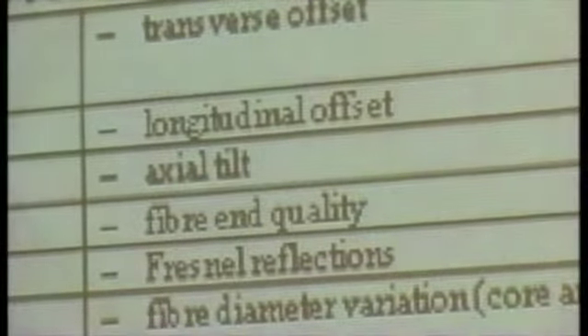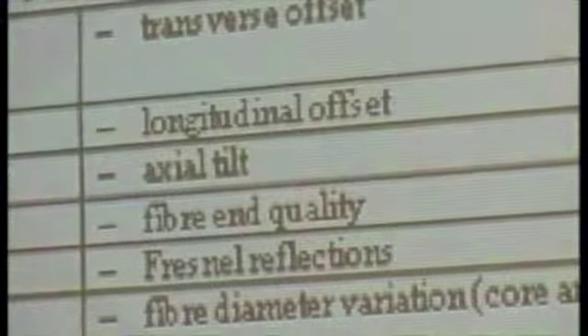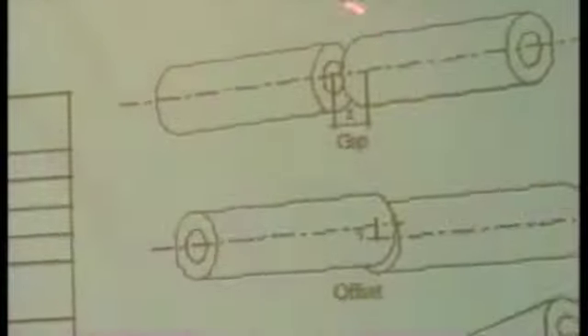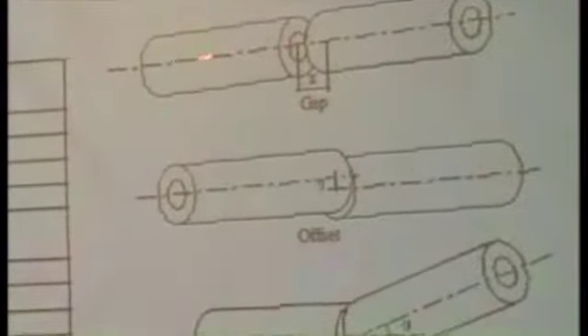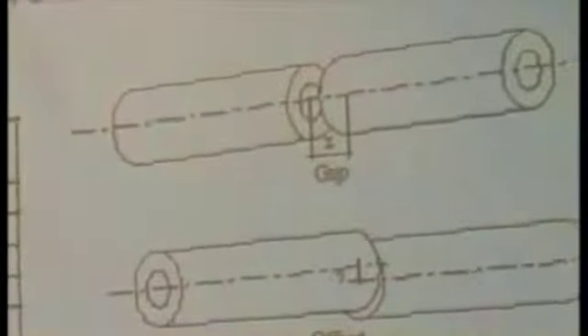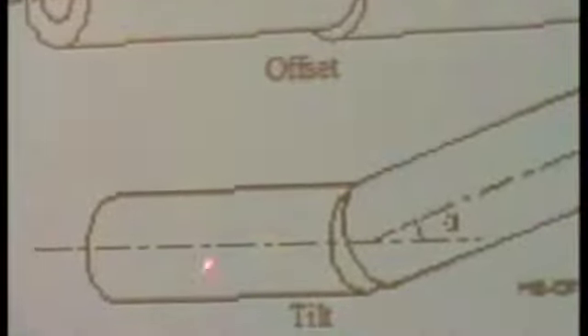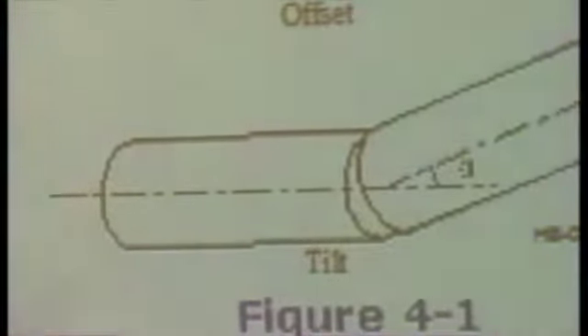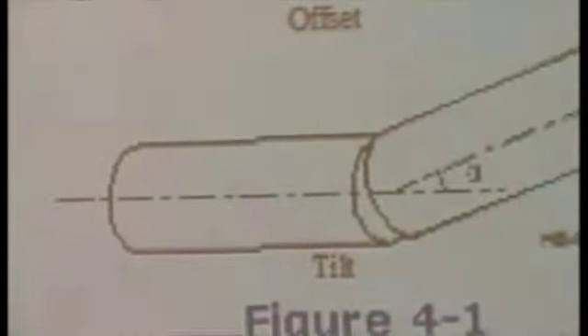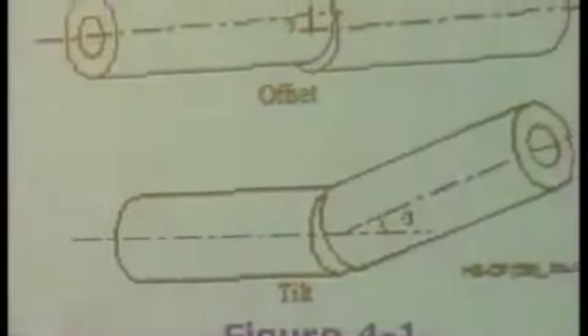In the interface, we could have transverse offset. We can find longitudinal offset, axial tilt, fiber end quality, Fresnel reflections. Just to give you an idea of what I mean: if you have two fiber ends, they could be a little far one from the other, and we can find a gap here. That will be the longitudinal offset. There can be some difference in the axes of both fibers, and also one fiber could be in one direction and the other with some tilt. These are considered extrinsic joint loss factors because they are independent of the fiber.